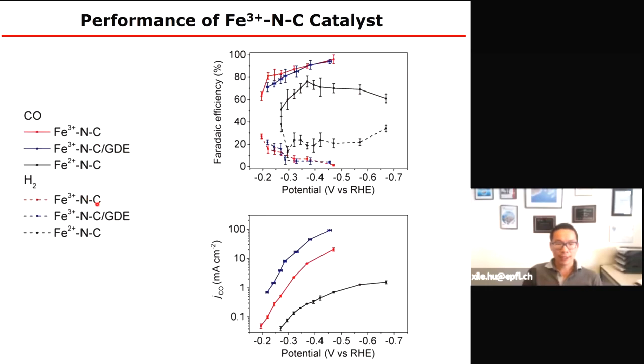They are much more selective compared to the literature iron 2 based catalyst. We looked at the partial CO current densities under the same conditions. The red curve is our iron NC compound, and the black curve is the literature-reported iron compound. We are certainly one order of magnitude more active. In fact, CO2 reduction to CO starts at an overpotential of about 80 millivolts, so really low. If we use a gas diffusion electrode, we can get higher current density, respectable at still relatively low overpotentials.